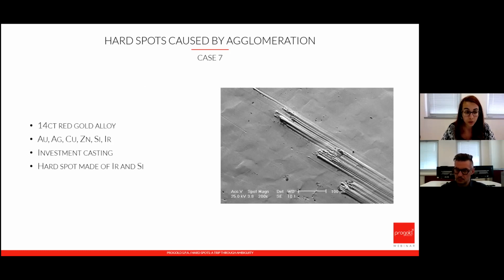It's very difficult to put it together with silicon. We have to respect a lot of rules. So in this case, we had a change of composition due to the reutilization of the alloy, and at some point, the quantities that we had inside were not good enough. So we ended up having the reaction between these two elements.